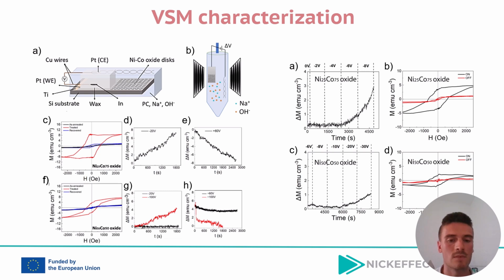In this case, the bias was minus 20 volts for the most cobalt-rich composition, and it created the same effect in terms of increase of magnetization as in the most nickel-rich composition, but with a 5 times larger voltage - instead of minus 20, minus 100.